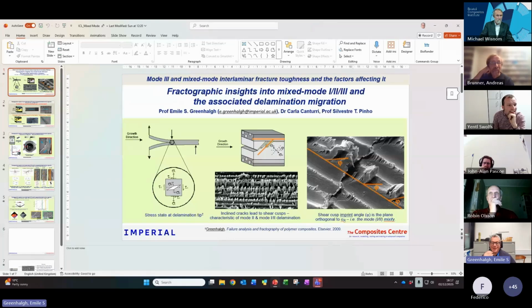Yeah, that was the principal focus of my PhD, to measure that angle and infer the mode mixity. The idea is that if you're presented with a delamination surface, you could characterize the cusp tilt angle, and they all tilt at the same angle. But it just proved to be very difficult to do that. This was in the mid-90s. But I think maybe with AI, you could look at a fracture surface and actually make that measurement and use AI to characterize the imprint angle.